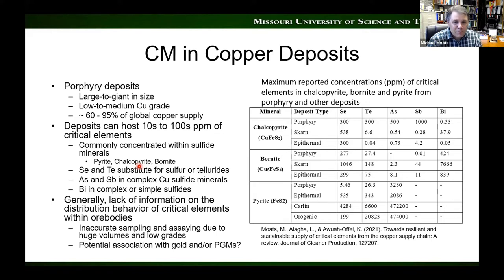But usually the selenium and tellurium are basically substituted into the sulfide matrix, the ones that we capture. Arsenic and antimony can create complex copper sulfides. So this is the enargite and the tetrahedrite. And bismuth can form complex sulfides or even be separate sulfides by themselves. When you look through the literature, there's not a lot of information. Now, I'm assuming companies have more information, but what's published in the literature is pretty scarce. And because of small sampling size for large deposits, assaying of PPMs, the question is, we don't really know.